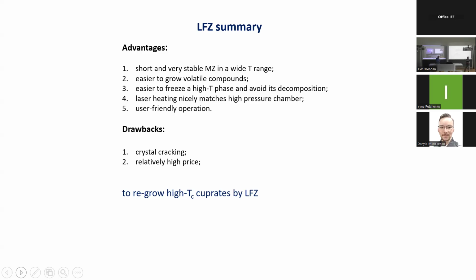Bernd, please. YBCO has been studied a lot, and a lot of people say they have fantastic crystals. I think there have been arguments that they indeed have good crystals, except praseodymium 1-2-3. I presume this does work. Nobody did the floating zone for YBCO before. It might lead to larger crystals, larger and much thicker along the surfaces. Yes, of course. We discussed making crystals large enough for neutron experiments. He remembers that in Keimer's group they did it long ago. That is actually that Nature Physics paper, where we compare this for YBCO, but we would be much happier to compare RIXS and neutron for this, of course.